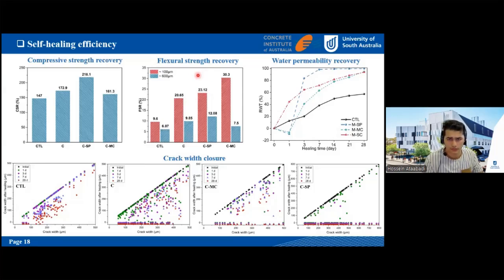We had two different crack widths in the flexure samples. One around 100 micron and one around 800 micron. So in both different crack widths, the performance of the capsule-incorporated sample was higher than the control one, showing that it has a very good efficiency.